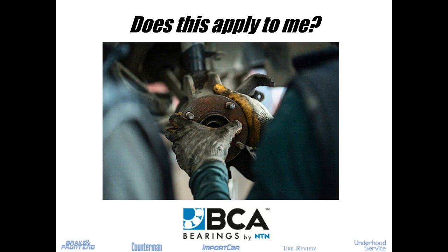This is Divjo Singh from NTN. For the ball bearing, the main difference with the roller would be that you have a point contact with the raceway versus the roller, you have a line contact. Whenever you have a line contact, you have more friction. So that would be the main difference, and you'll see heavier or more friction with the roller bearings.